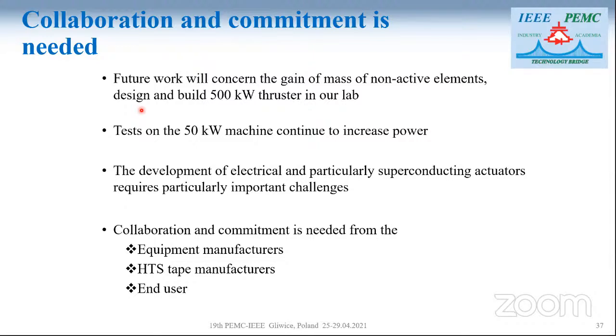And the main problem for HTS tape is not exactly only the cost. The main problem is that the width of the superconducting tape is 4 millimeters. If we want to reduce AC losses, by example using superconducting tape in the armature, you need to have 0.1 millimeter for the width of the tape, and for the moment, it's very difficult to obtain.